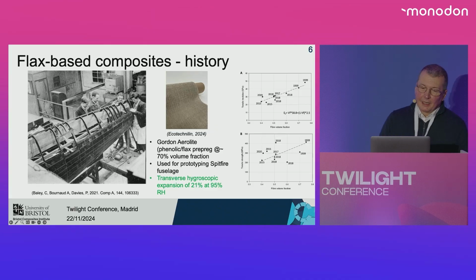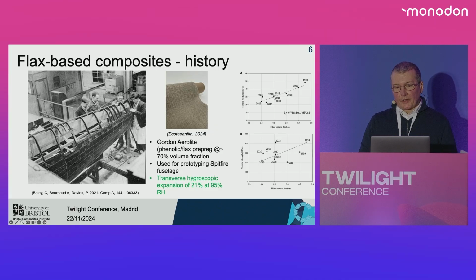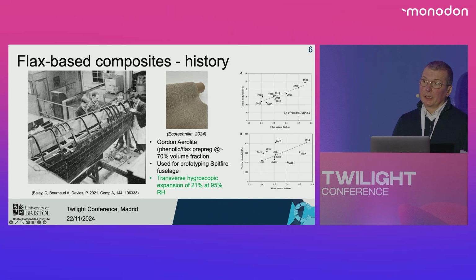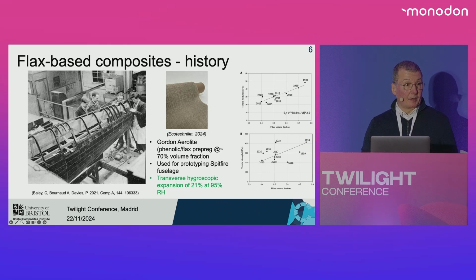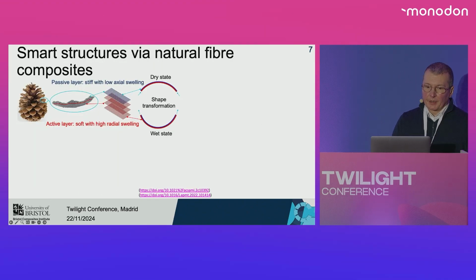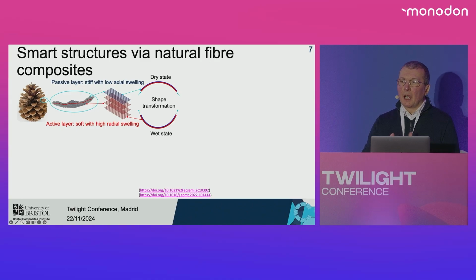Quite interesting, flax has got a hygroscopic expansion of 21% at 95% relative humidity, which is the largest among the technical natural fibers that you can find around. So it's an interesting type of reinforcement, and in terms of adaptive structures, nature really suggests a way to use these types of natural fiber composites as actuators. And the inspiration comes directly from the architecture of the pine cone scale.